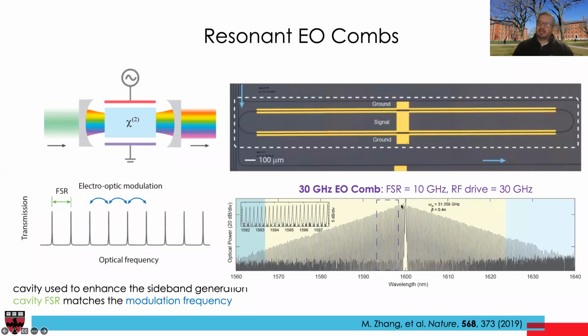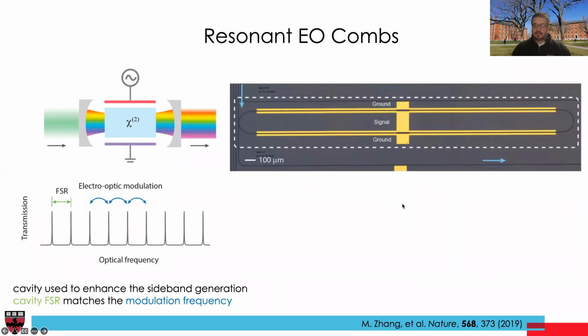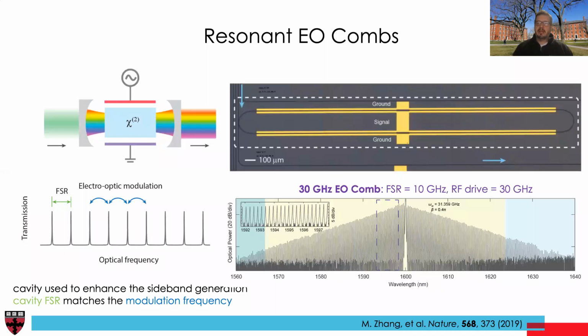The issue here is that this comb is not very efficient. In fact, if I were to show you the pump on the same scale, you would see that the efficiency is below 1% here. It's like 0.3% or so. But the comb spectrum is much broader than what we showed you before.